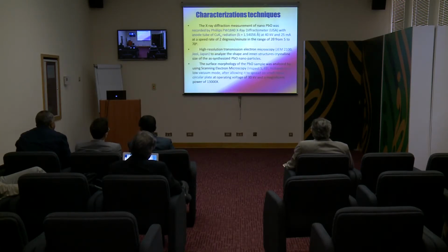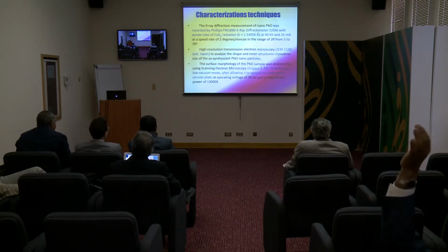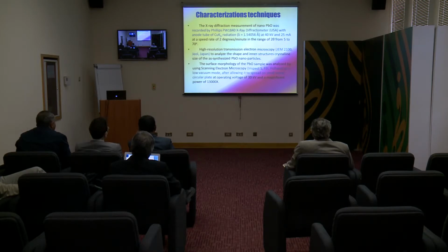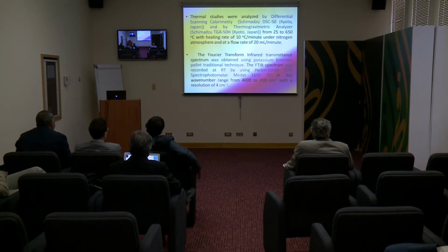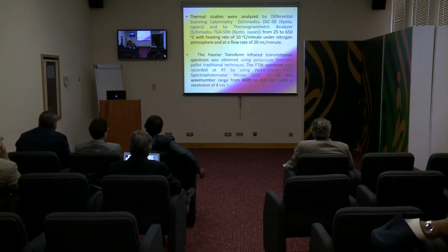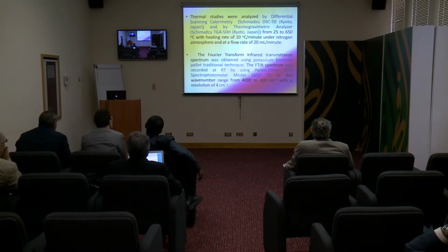Characterization systems used in this study: X-ray diffraction with a speed rate of 2 degrees per minute in the 2 theta range from 5 to 70 degrees. High resolution transmission electron microscope to analyze the shape and inner structure and crystalline size of lead oxide. The surface morphology was analyzed by scanning electron microscope operating at 30 kilovolts and magnification power 13,000. Thermal studies were analyzed by DSC, from 25 to 650 degrees with a heating rate of 10 degrees per minute under nitrogen atmosphere.